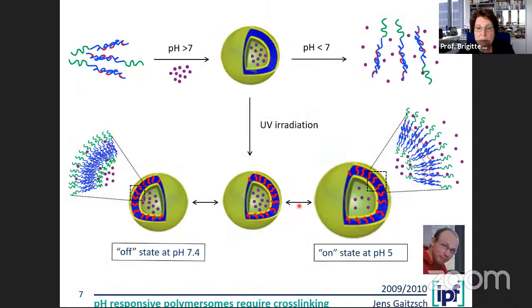We addressed specifically in my lab material which is pH sensitive. So you have a pH sensitive block copolymer, which is under certain conditions water soluble, and when you change pH, it becomes amphiphilic. And as soon as it's amphiphilic, it can, under the right conditions, assemble to a vesicle. And we wanted to come from a vesicle which assembles and disassembles to a more stable structure, a nanocapsule, which can actually reversibly swell and deswell. And for that, we introduced UV irradiation to cross-link the membrane after the assembly.